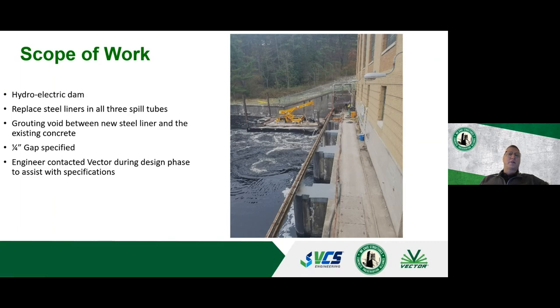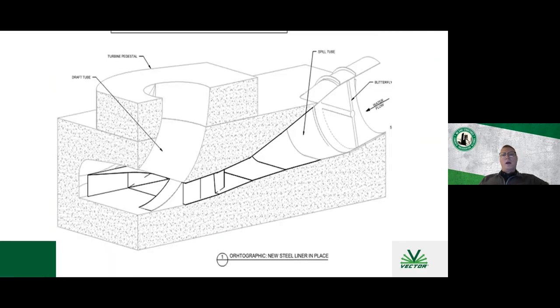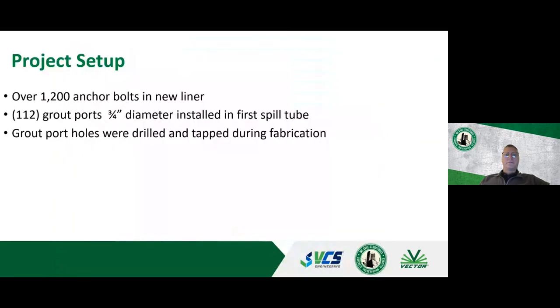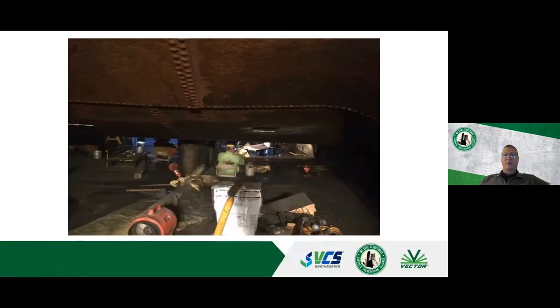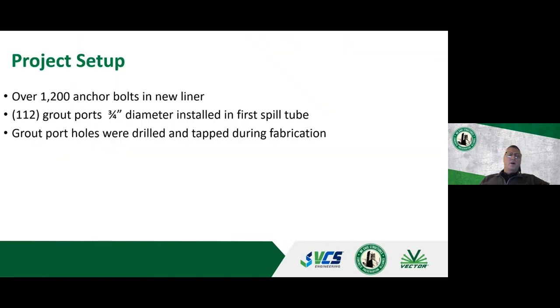So they added the steel liner. Well, the steel liner has a 1/4 inch gap behind it, which creates cavitation and other issues. When you install the steel liner, the darker areas show where it gets installed. There's the steel liner. Wonderful work environments. We were about 3 foot tall at the highest point. We had 1,200 anchor bolts and added 112 grout ports, 3/4 inch. These aren't very wide, 3/4 inch diameter ports.